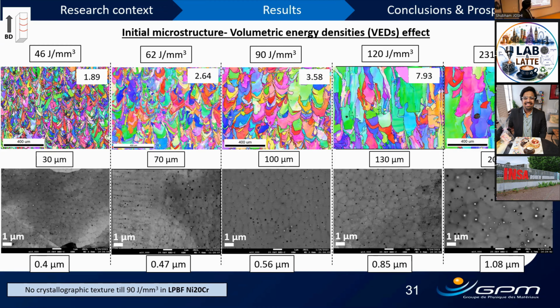Yes, we did not quantify the morphological aspect. It was a qualitative analysis to see that clearly the morphology seems to be changing. But using the average of the two, again, this is a very crude assumption that we can take the average of grain size in different orientations, so in the XY plane and in the XZ plane. So certainly there could be a sensitivity in terms of a correction factor of aspect ratio, which could improve the model. But as of now, I cannot direct you towards the quantification of this factor.